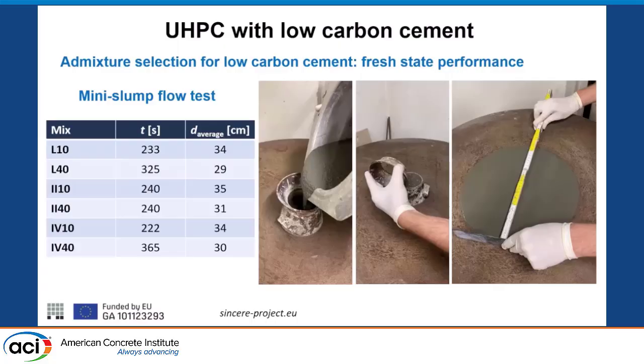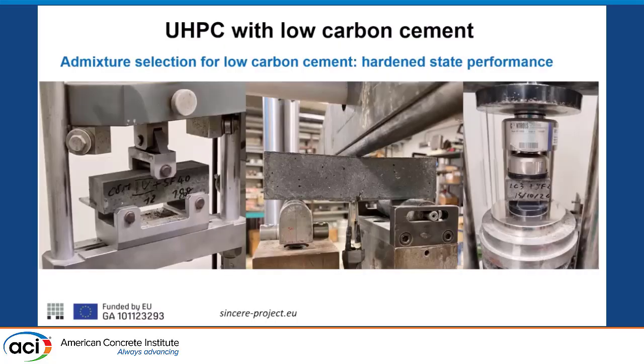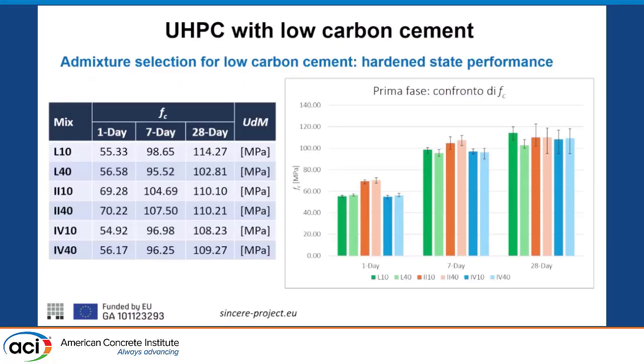But this is just the cement paste. Then you have to go with the mortar, then you have to add the fiber. So we needed this in order to get a good consistency. And we also wanted to see, okay, what are we obtaining in terms of material properties, especially, not very early ages, because we did not have for this kind of intervention very intense productivity requirements, but if you make a jacketing, you want to take out the molds of the jackets quite soon. So we tested small specimens at the beginning. These are the 4 by 4 by 16 centimeter beams, and then you perform the compressive strength.